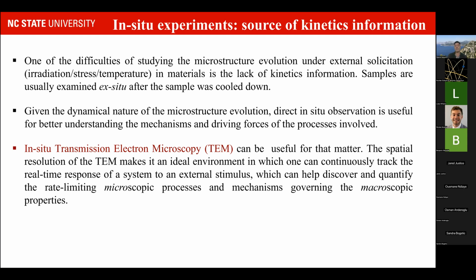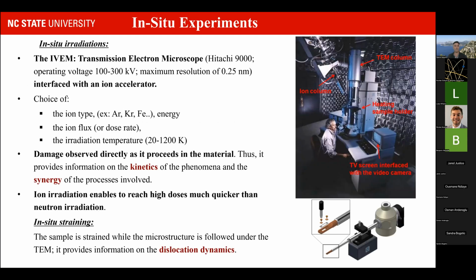So given the dynamic nature of the irradiation effects, direct in situ observation is in fact useful, if not necessary, if we want to really get to the mechanisms and driving forces that are involved in those processes. And this is where transmission electron microscopy can help, because the spatial resolution of the TEM makes it ideal to continuously track the response of the system at the mesoscale. And for me, mesoscale, I say for me, because I understand that for other people it might be a different scale, for the microscopist, the mesoscale is going to be anything in the nanometer to the micron level. And we can try to relate that to the macroscopic properties.